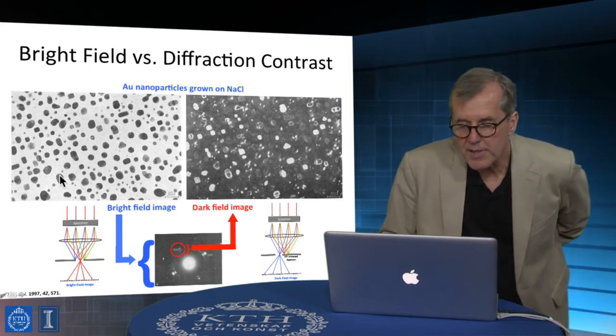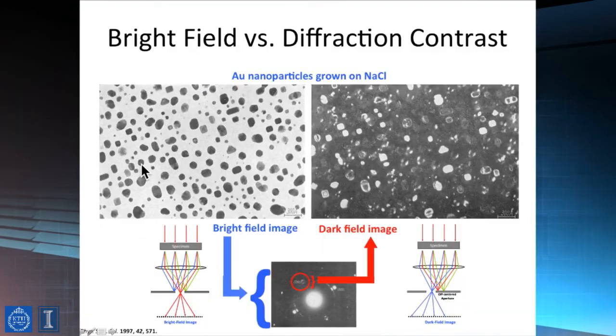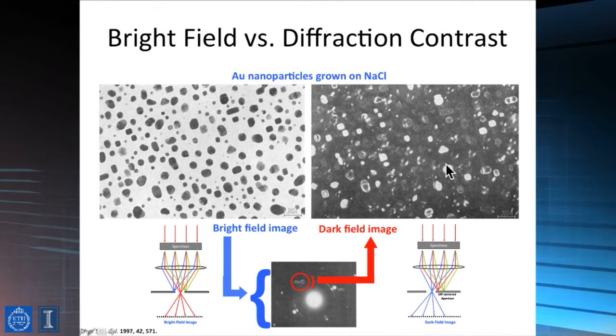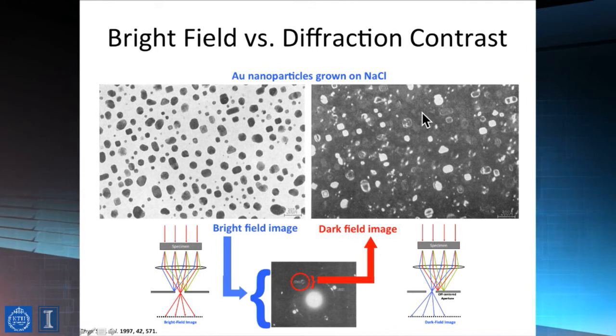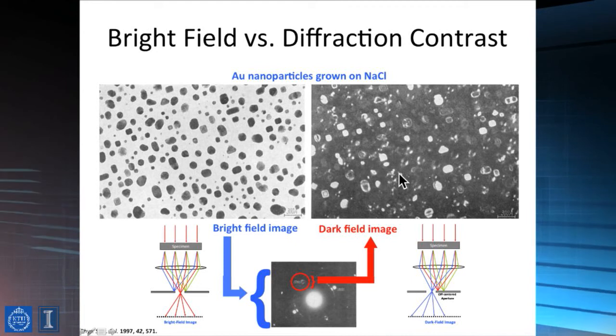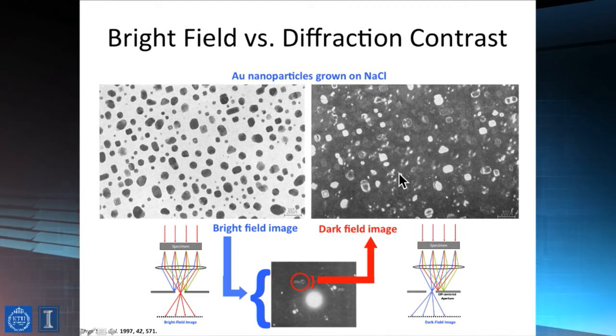But having said that, we notice that, for example, some things look almost hexagonal, some things look square, and obviously there are different crystallographic polymorphic conditions being evidenced here. We can look at diffraction orders and pick one, and then look to see what the image looks like by taking those electrons and constructing the image. And basically what you see in this case are only specific diffraction related conditions.